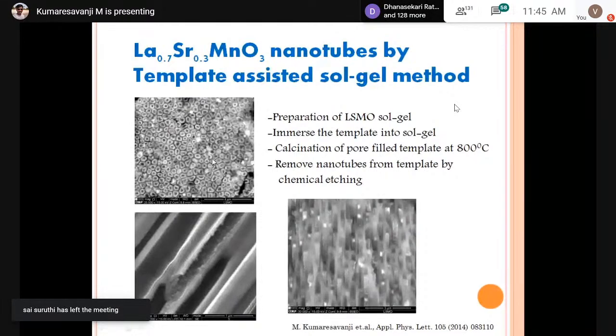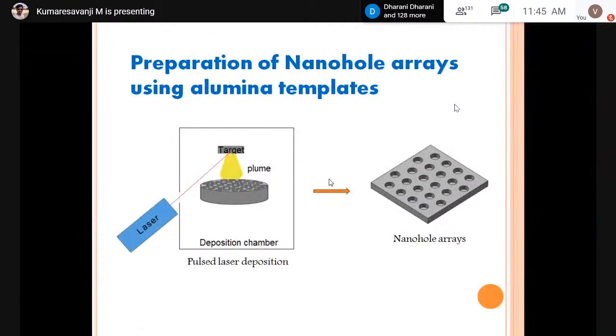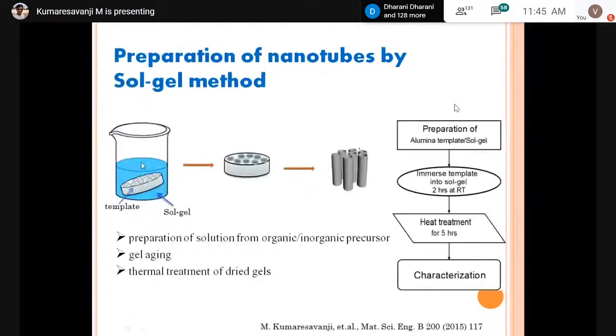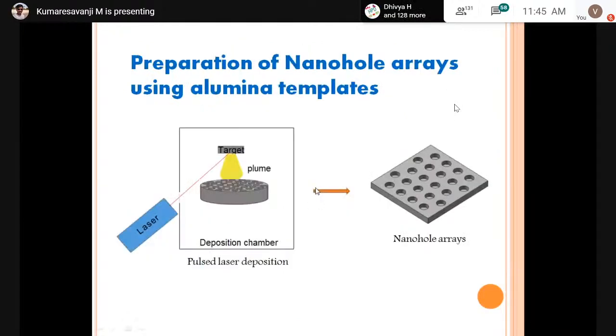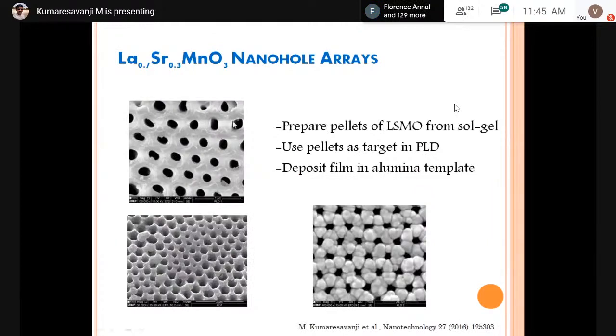Another thing I have prepared is nanoporous films. I can prepare them from the same sol-gel. I told you about the sol-gel, right? You dry the sol-gel and you get an aerogel. Then you calcine it and you get nanopowders. Then you press it to make a pellet. The pellet is used as a target in pulsed laser deposition, and you aim the pulsed laser at your target. A plume is created which will deposit on your nanoporous alumina template. So a nanoporous film is nothing but a continuous thin film, but with ordered nanopores in it. Okay. Here I show some SEM micrographs that I have prepared for lanthanum strontium manganese oxide nanoporous films.